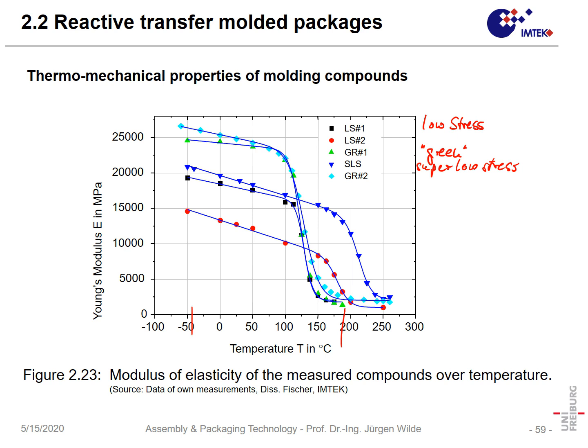So, if we raise the temperature, we have more or less a linear behavior, and in all molding compounds it goes maybe down to 100 degrees centigrade. Then, depending on the material, first of all, we have large differences in between these materials in Young's modulus, and the main factor determining Young's modulus here is the content of silicon oxide. We can see here that material goes down until 150 degrees centigrade.